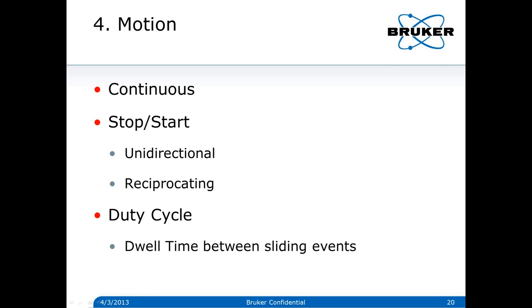For example, with a crane rail wheel, the flanges come in contact but not all the time. The crane may move down to one end of the shop, sit there for a few hours, and then move back — so you have a duty cycle with much more rest between actual rubbing events, maybe 15-20%. In other cases something is functioning all the time and the duty cycle is near 100%. If we shorten the duty cycle to speed up the test, we just need to consider the actual duty cycle in our wear coefficient calculation.